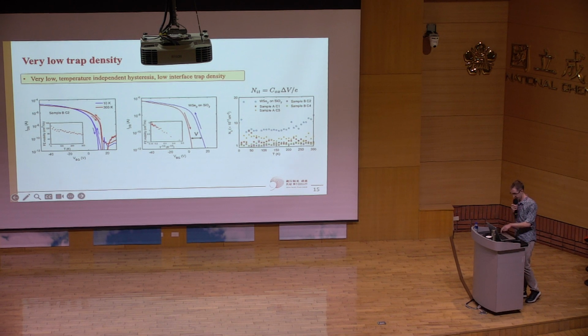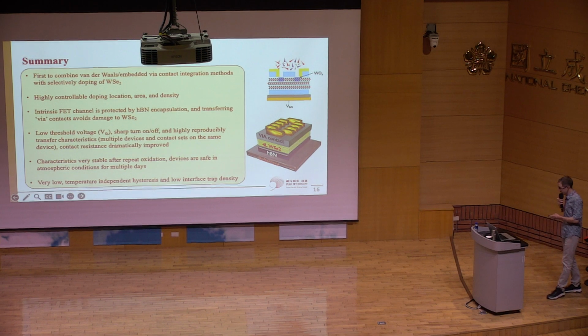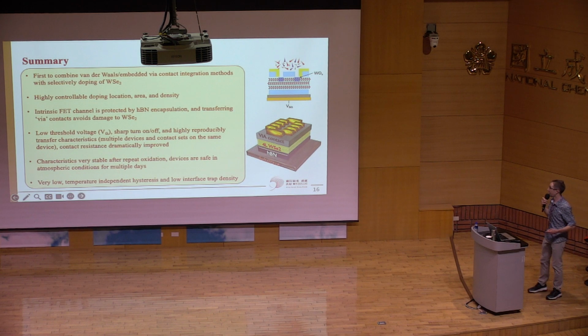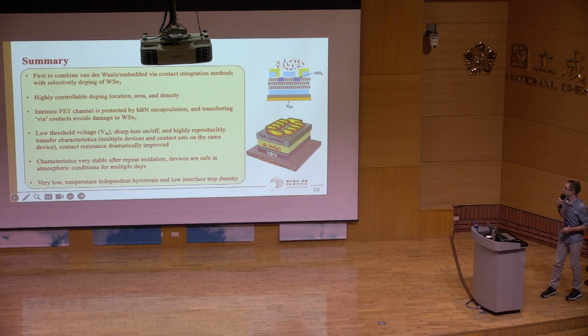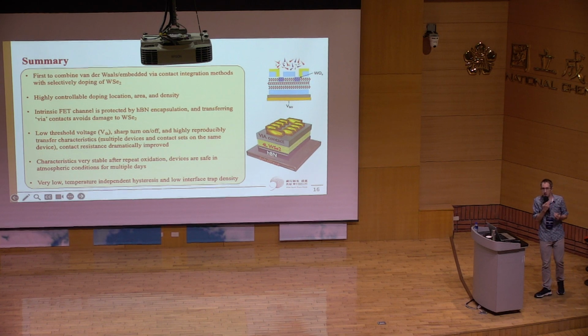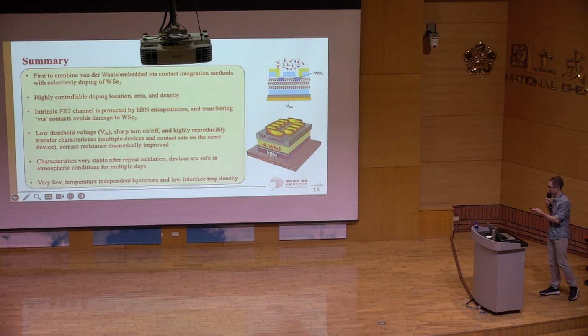Now, just to summarize, there are a number of firsts in this work. That is, it's the first to combine these transferred contacts with the selective doping, and we can control precisely the doping location, area, and density. We protect the channel, which is very important. We achieve threshold voltages which are very close to zero, and that appears to be quite consistent in all of our measurements, and it's very intriguing and worth investigating further. And we create very stable devices that we can leave in atmosphere, and they're safe for multiple days.